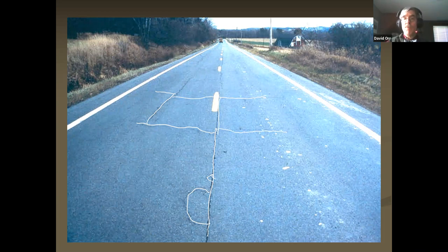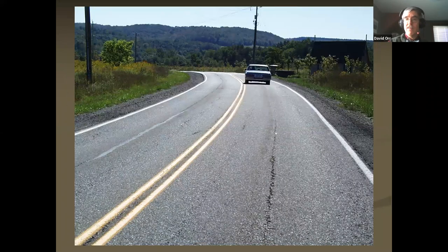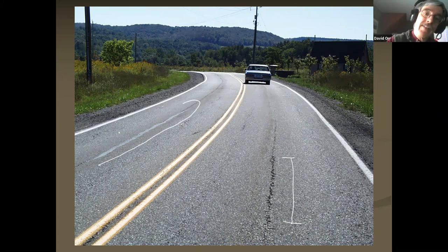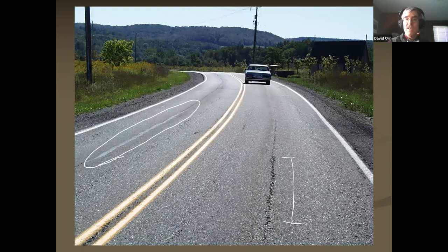It's still okay. You don't have more than two parallel cracks at any one location. But anything beyond that, there's just too much density, there's just too much work, and you actually could create a safety hazard, okay? Now, something you'll see a lot is you may actually see cracks that aren't wide enough. This is actually a reflective crack from a lower layer. And while it's wide enough in this zone right here, overall, this crack is probably not quite wide enough. You can see where they've tried to do a repair over here in the left lane, but it's just sitting on the surface. It didn't get any penetration, and you're not getting any reinforcement of the adjacent material for a crack fill. And of course, there's no ability to flex if there's any movement. I will admit most reflective cracks tend to move with whatever the crack below is doing.